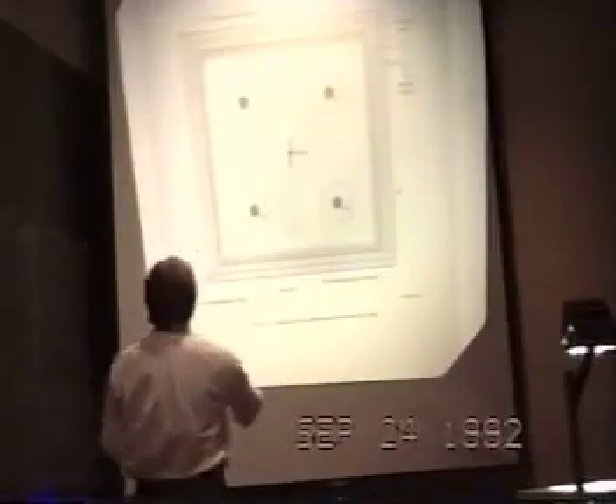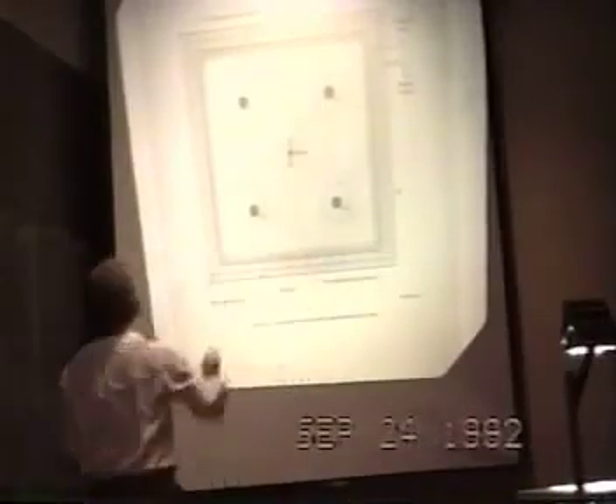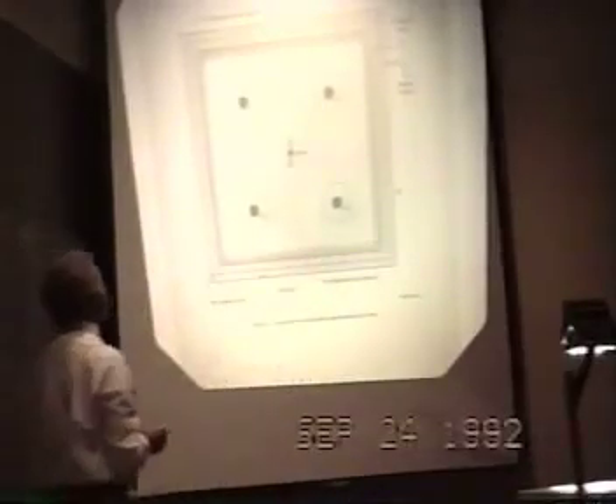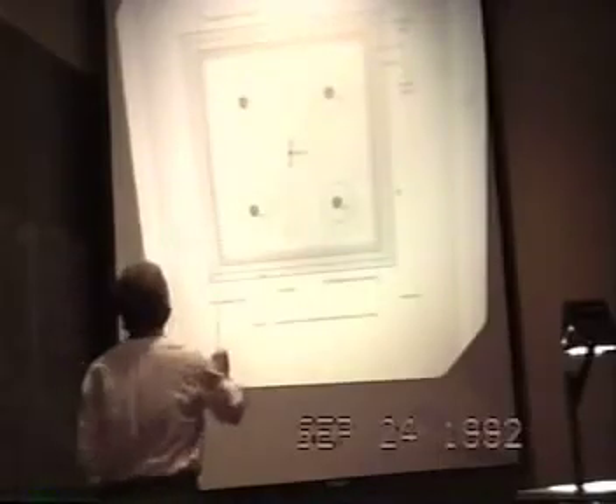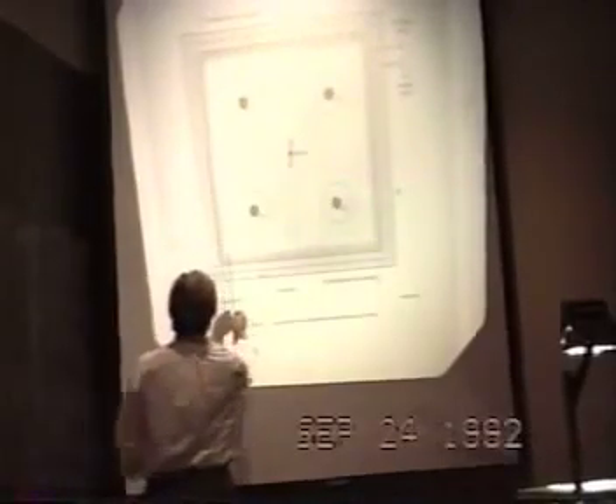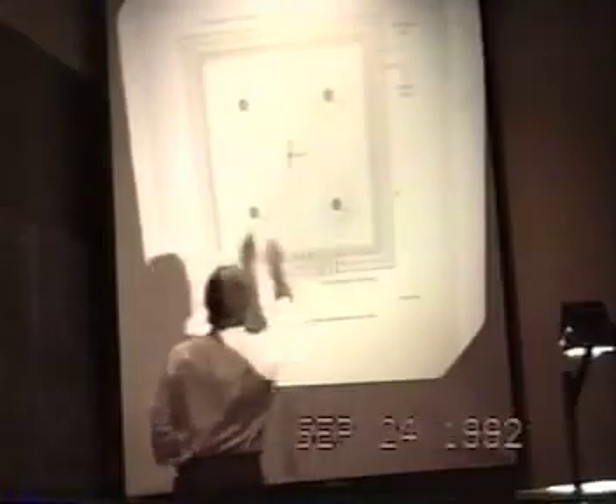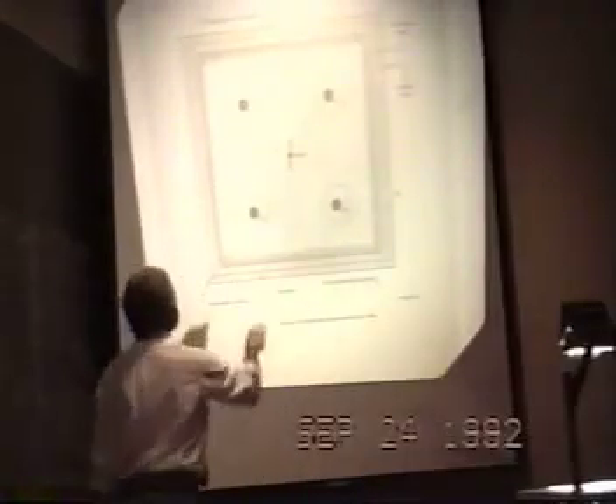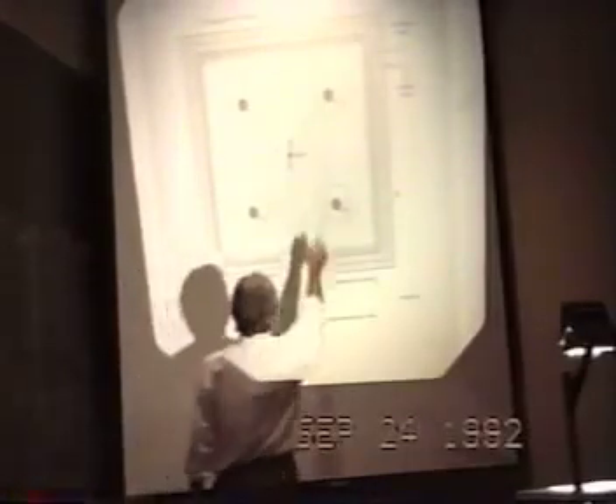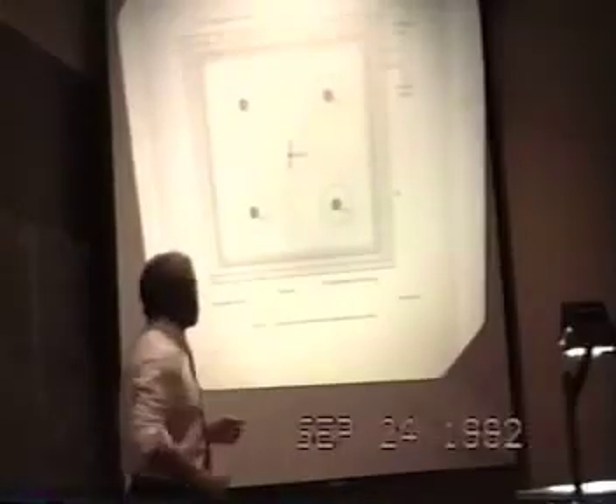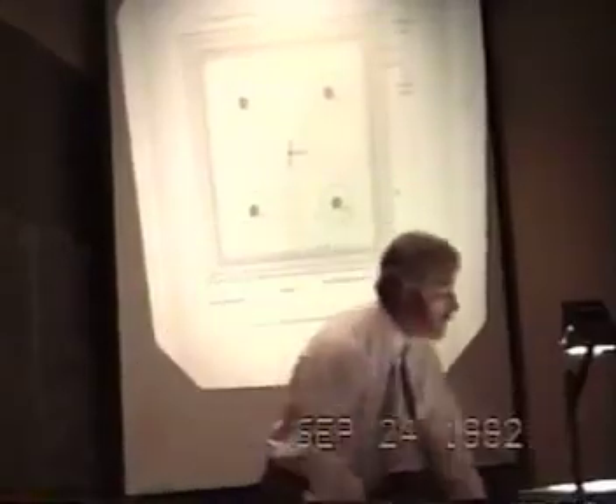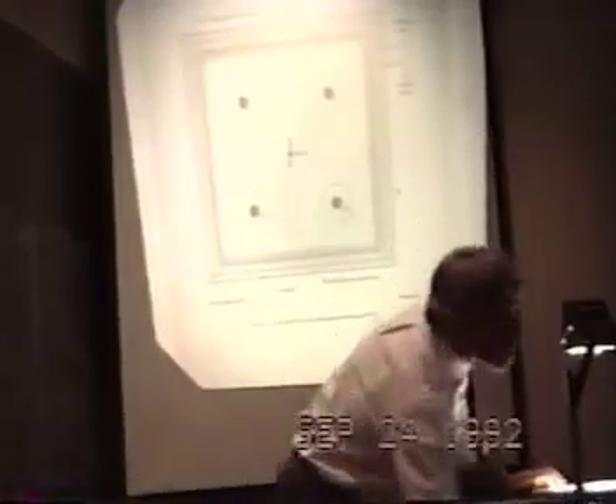What we did was take a large bath that's about a meter huge, in fact. You're looking at it from the top. The bath is maintained at constant temperature with respect to heaters on the walls. We place in this bath up to 4 calorimeters in a well-stirred environment. The bath is maintained plus or minus 3 millidegrees long-term and short-term.